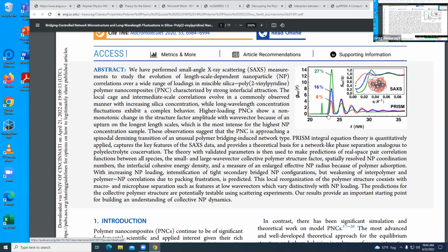So anyway, what's missing here in the whole scheme is that the silica is charged at the surface. It's got a pretty heavy surface charge, and that's really the origin of this peak. A large part of the origin of the peak is the surface charge, which is completely ignored in this, explicitly. So he just has energy polymer, energy particle, energy particle-polymer. It's got 3 energies, which is typical for any simulation. But one of the energies, the ionic energy, is governed by the screening length, the Debye screening length. And the more particles you put in, the more ions you have. So the screening length gets smaller. So the interaction between particles decreases with particle concentration, because as you add the silica, you're adding ions.